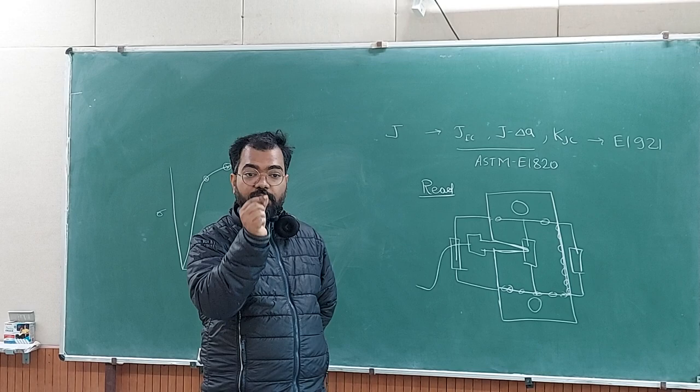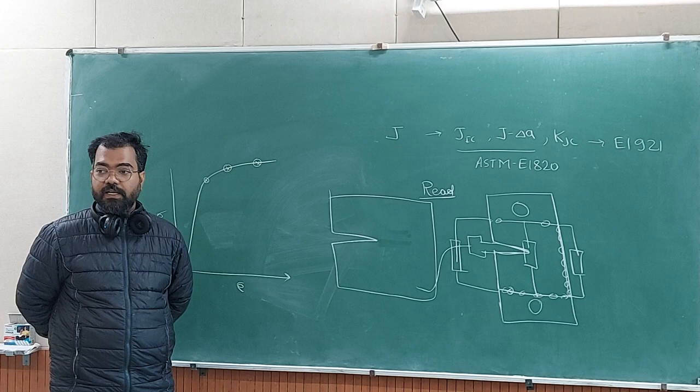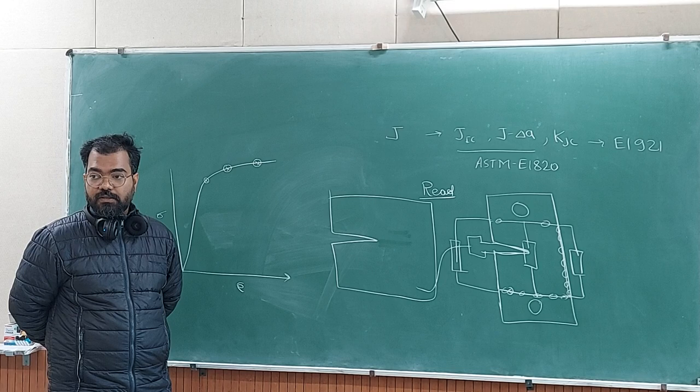If this is the sample, a metallic material, then you polish this surface before doing the fatigue pre-cracking. You don't have to do very good polishing, because you don't want to see the microstructure there, but enough polishing you have to do using emery papers, so that it becomes reflective.